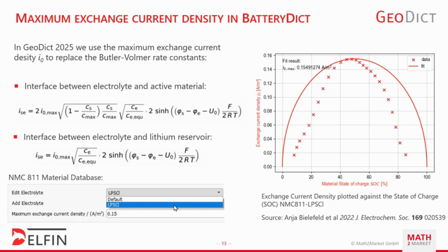In this case, you can see how we fitted our maximum exchange current density against data which we got from Anja Bielefeld from the University in Giessen. So we take this data, we analyze it, and then we put it into the material database. Of course, it has to be said that you need to put in this information with every pair of active material and solid electrolyte. Okay, these are some of the equations which get simplified, which I just mentioned beforehand.